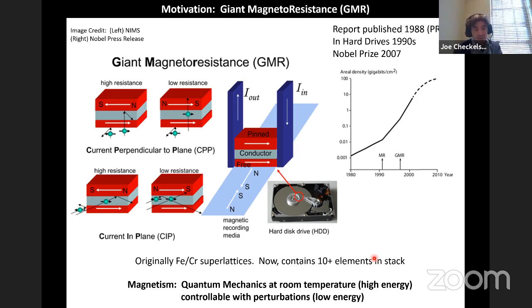And what was done in the 80s was people realized you could make these little sandwich structures of magnets. Here you have one magnetic layer separated from another magnetic layer by some spacer. And what was found experimentally was the electrical resistance of these little sandwiches was very different if the magnetic orientations were the same or opposite. And so this was interesting. It was a so-called giant response. This electrical response was so big.